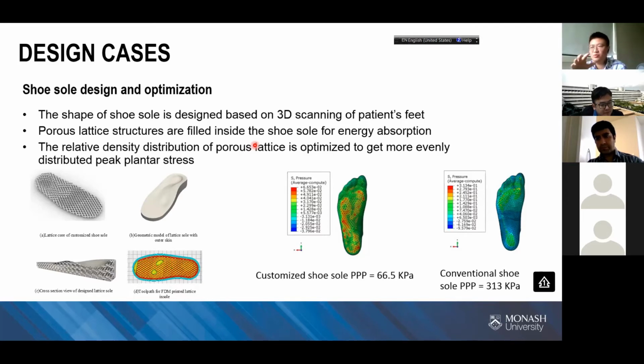The idea for this one is that we want to use the lattice shoe sole for energy absorption, but we also want to control the properties along the sole. If we look at our sole, on different regions, having different mechanical properties can further help us lower the PPP, the peak plantar pressure on the bottom of our feet. So we developed an algorithm based on a theoretic model to help us optimize the porosity of this type of lattice structure to further reduce the PPP, peak plantar pressures.